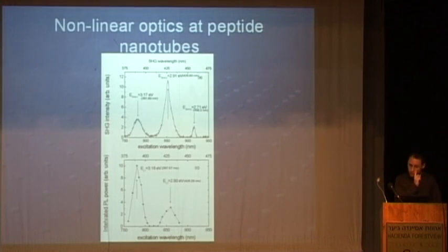The second harmonic generation that we receive is not the usual second harmonic generation which occurs in regular crystals. It's an excitonic-like second harmonic generation. We can receive it only when we excite at certain wavelengths. By the way, the excitonic location matches the excitons that we found when I started to talk. You just need to divide the values in two, and then we receive exactly the same location of the excitons that we received in our previous studies. And also this unique super photoluminescence is excitonic-like in origin, meaning that you can excite it only at certain points.